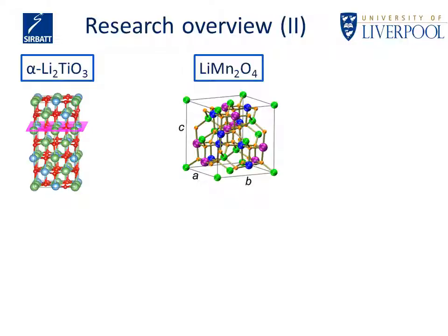In addition, we studied lithium manganese oxide, which is a good candidate of cathode material to be implemented in future designs. This is because lithium manganese oxide has a high operational voltage, is lighter for a given capacity, has a low safety charge, has a lower cost, and is environmentally friendly. However, this material undergoes degradation that affects its lifetime.